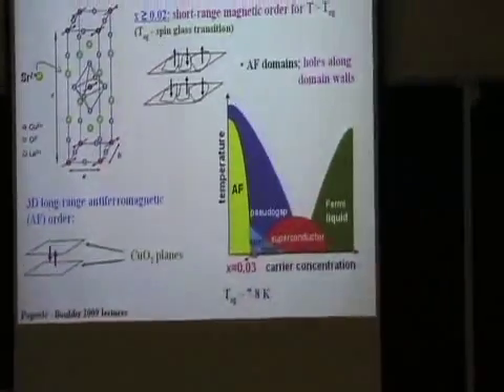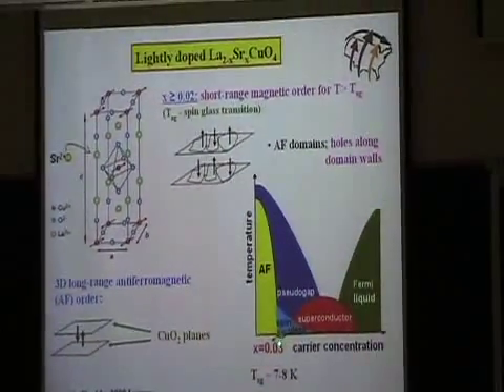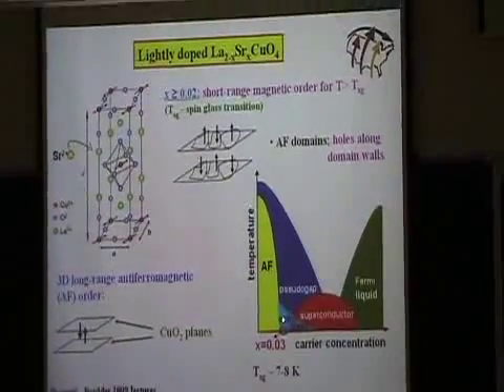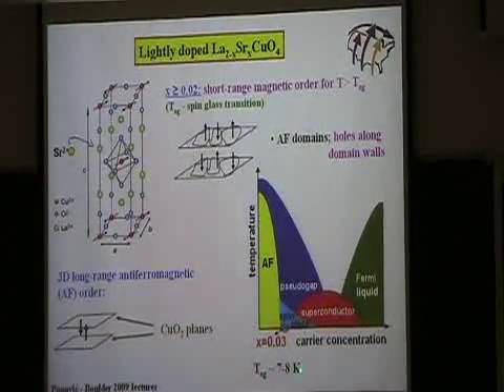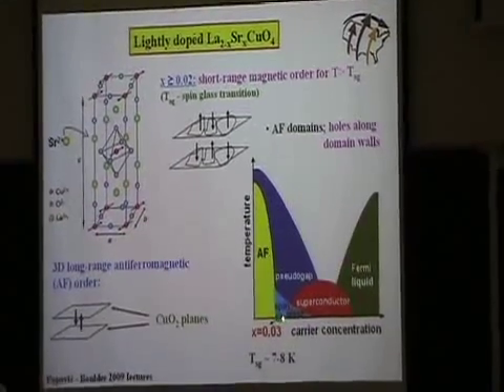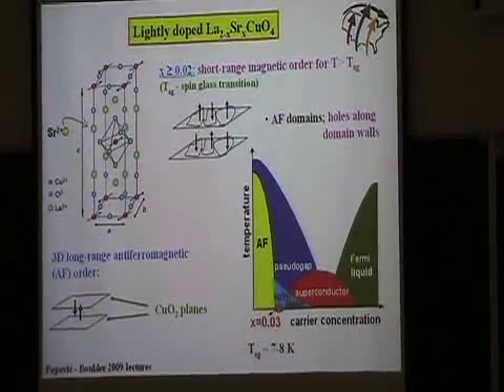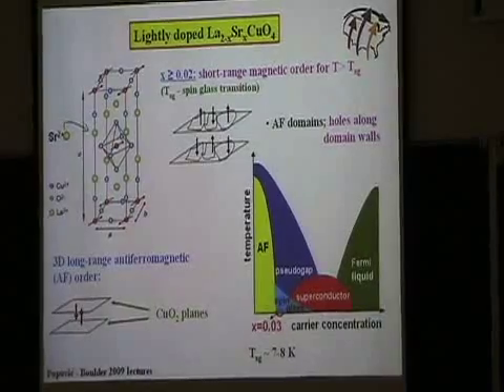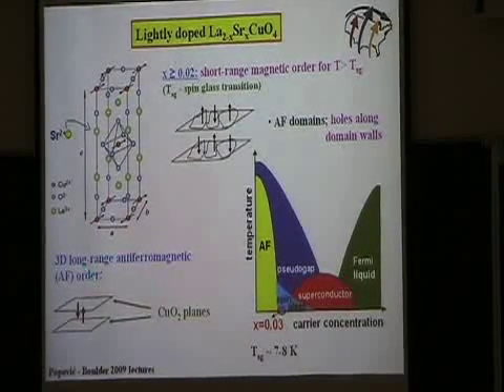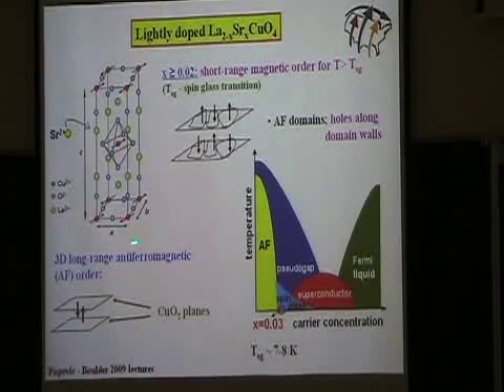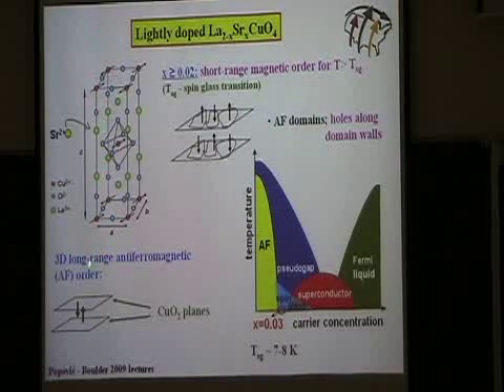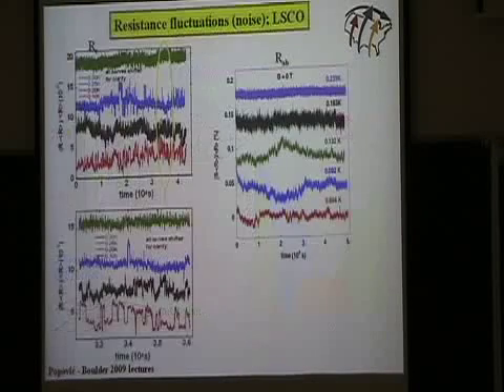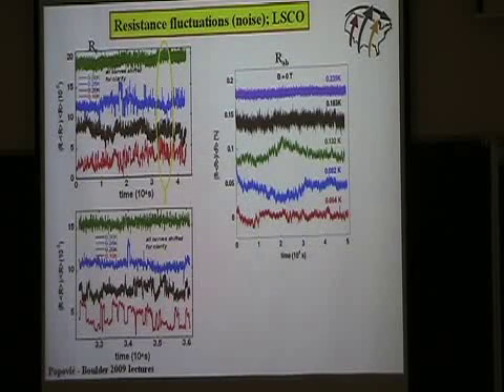Okay. So what we want to do, we want to work here. 3% doping where we know we are in the spin glass regime. So we work at temperatures below the spin glass transition temperature. And the system is insulating. So what we do, we measure transport. You can measure transport in the plane. And you can try to measure transport along the c-axis or perpendicular to the planes. So here is an example, a more tedious measurement. So this is the so-called out-of-plane, and this is in-plane.